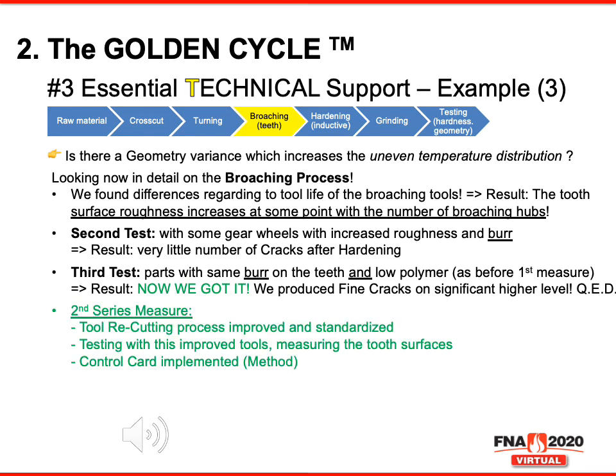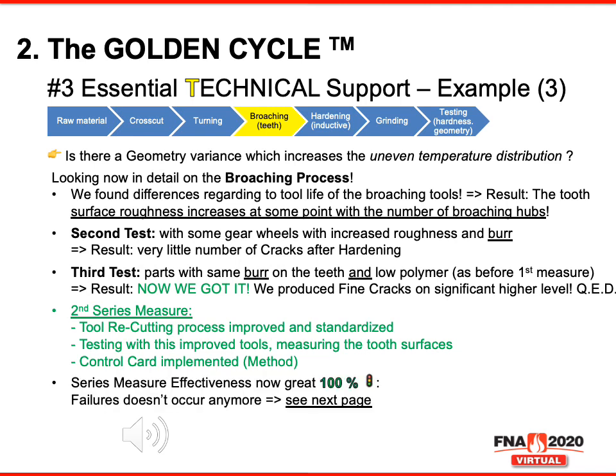The second series measures we implemented were that the tool recutting process has to be improved and standardized. Then testing with these improved tools, measuring the tooth surfaces, everything was well, and we implemented another control chart for the tool recutting process, or better to say, the number of broaching strokes. The series measures in total with the polymer concentration increase, the inductive hardening process was now a great 100%. Failures don't occur anymore, and that's what I would like to show you on the next page.